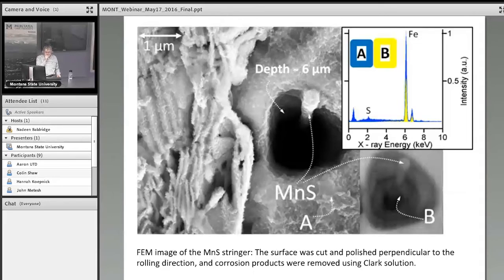So that's one message. The other one is you can take a spectrum from point A on the surface here. You can take another spectrum from the bottom of this pit. The blue is spectrum A, taken from this location. Yellow is the spectrum taken from the bottom. We are the only ones who discovered this, published it last year, I think. Comparing the two spectra, we can tell you how deep this narrow pit is. Turns out that this was 6 micron deep. So it's another method.